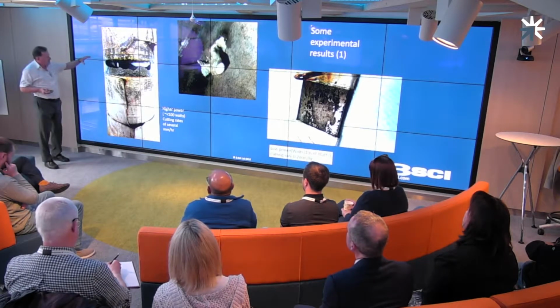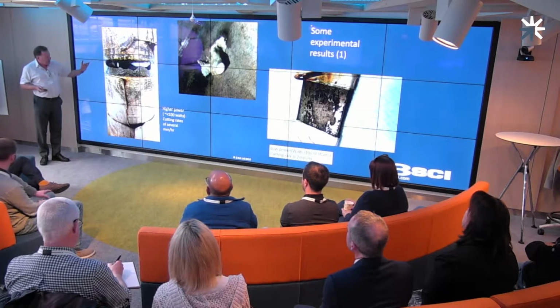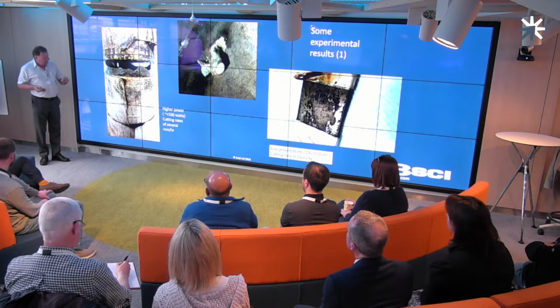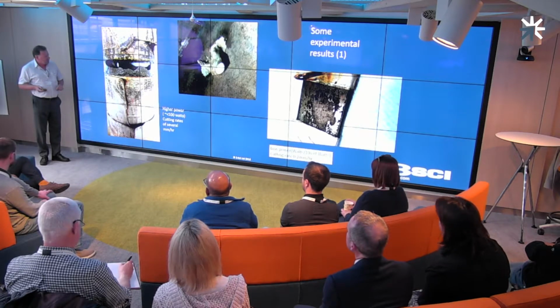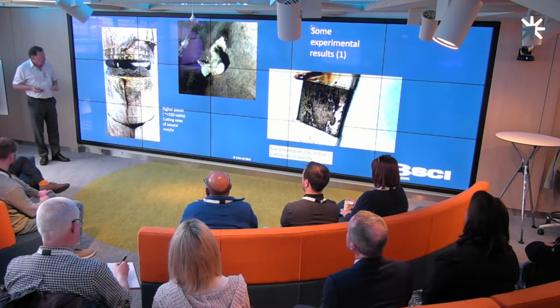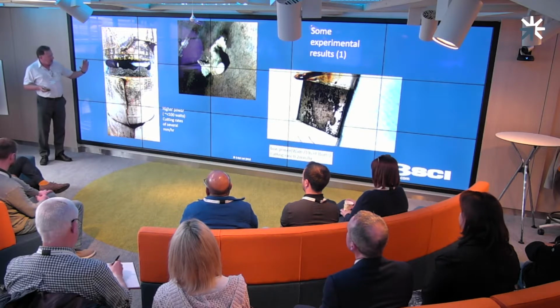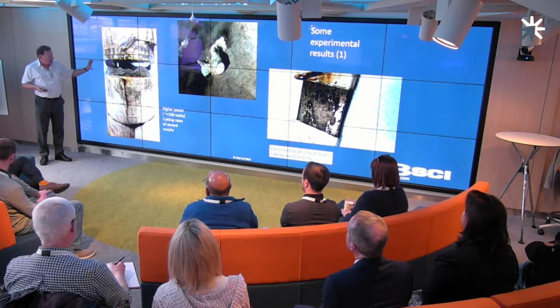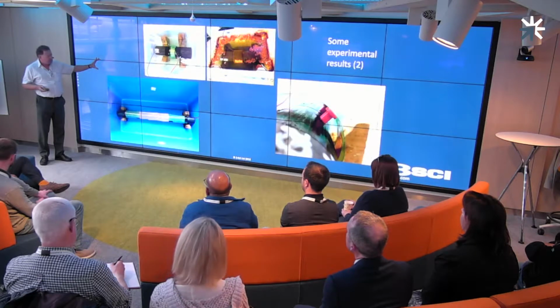In this case here, we have a piece of scaffolding, so that's about 2.5 inches diameter, probably about 1/4 of an inch, 6mm wall thickness. And by arranging a copper cathode as a ring placed around that scaffolding, the scaffolding disappeared probably in less than an hour for about 60 or 70 watts of power delivered to that circuit.